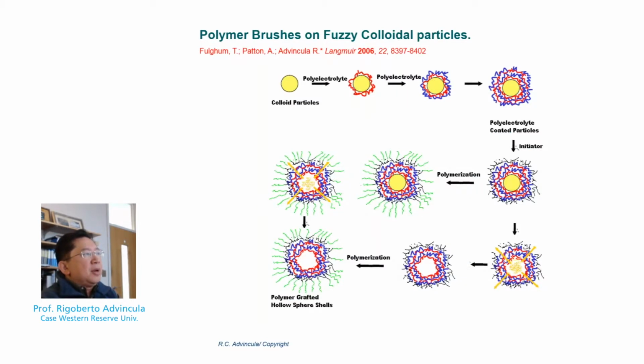Here is a particular paper where we published the grafting of polymers on a polystyrene particle. The idea is to coat the colloidal particle with polyelectrolyte macroinitiators. The macroinitiators are then capable of polymerization, therefore resulting in a core shell particle with a polymer brush shell. And in principle, it's possible to get a hollow shell geometry, although this was achieved by other groups, wherein after grafting the polymer on the surface, one can digest or remove or simply dissolve the particle to produce this hollow shell.